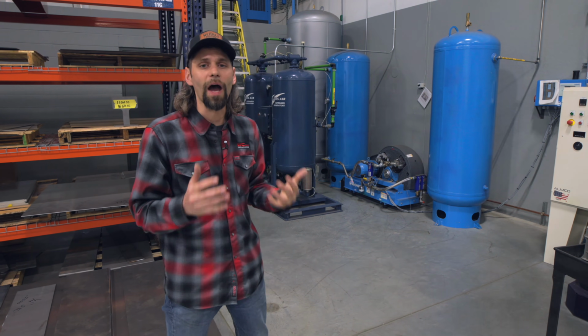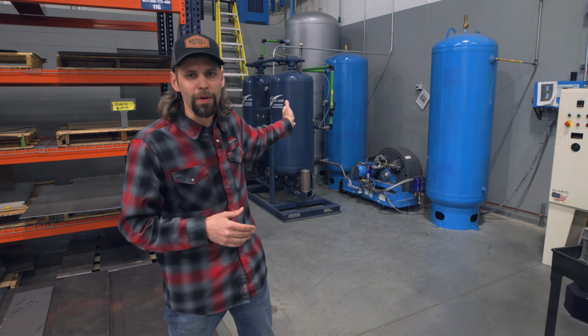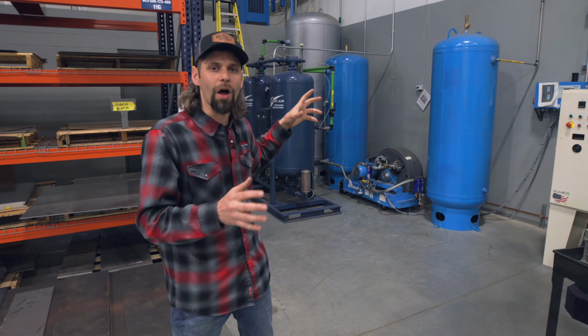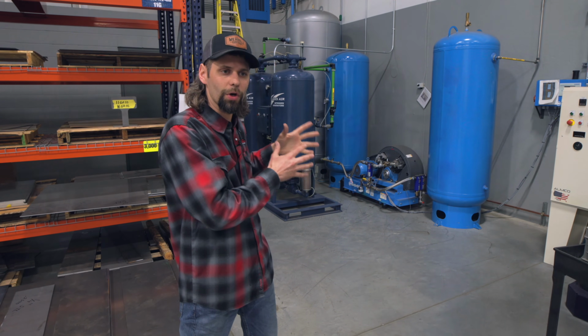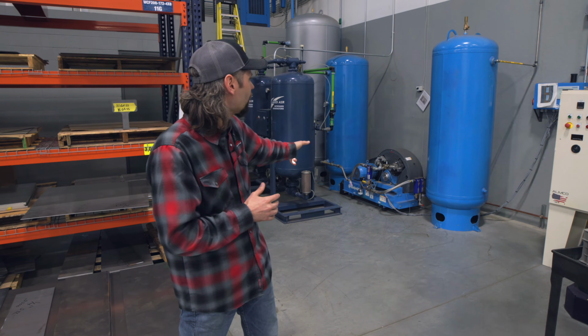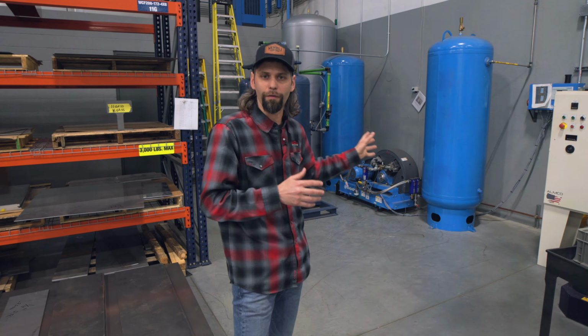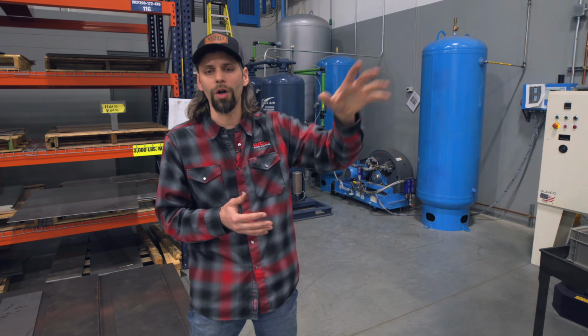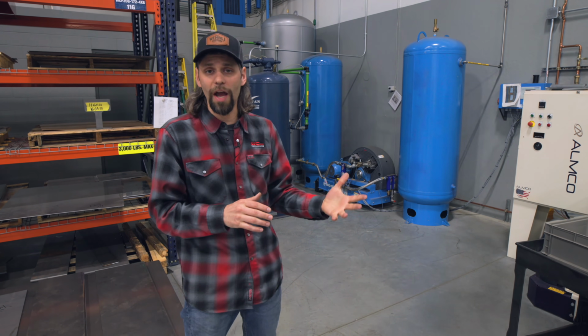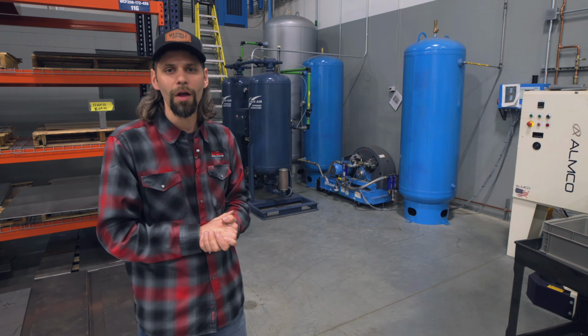In order for the machine to use this shielding gas, it needs to be high pressure. So it takes our 175 psi shop air, filters out everything else, and gives you 99% pure nitrogen. And then it has a high pressure generator bumping it up to about 380 to 400 psi. So we're feeding roughly 400 psi high pressure nitrogen to the laser for that shielding gas, specifically when we're cutting aluminum. And we cut a lot of aluminum in this shop, probably close to 60% of what we're cutting on the laser is aluminum. So we go through a lot of nitrogen, which is why it made sense to have this generator in-house versus having the bulk storage outside.